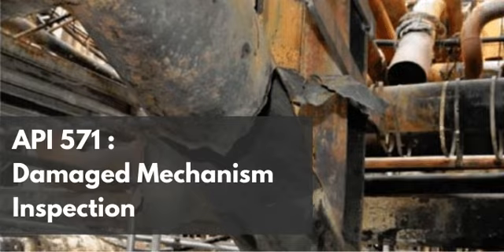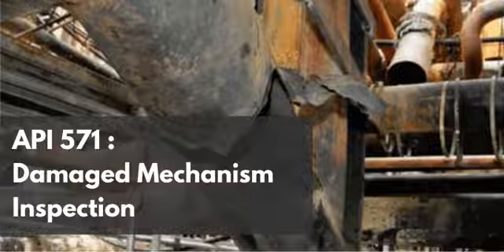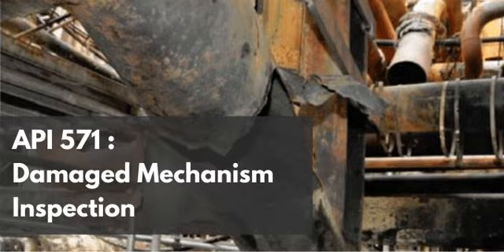In this context, absolutely, and for very specific metallurgical and fluid dynamic reasons. The visual evidence of this is striking. When you review the failure data, specifically the examples often documented as Figure 321, it shows severe, violently localized amine corrosion directly at the weld in the piping, running from the reboiler to the regenerator tower in an MEA unit.